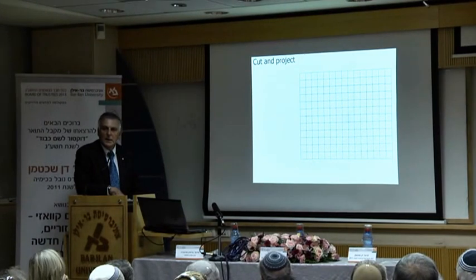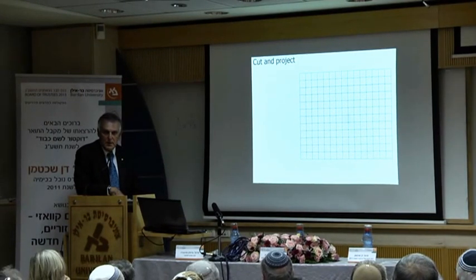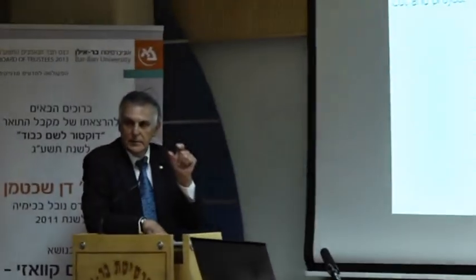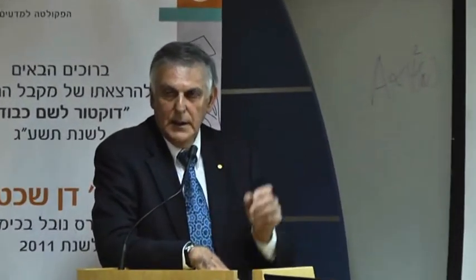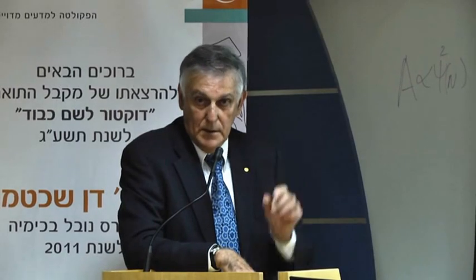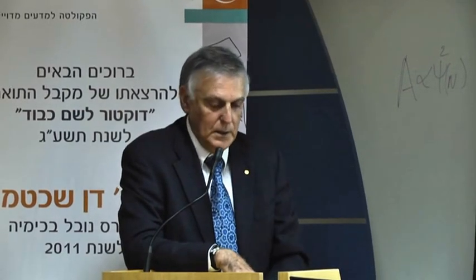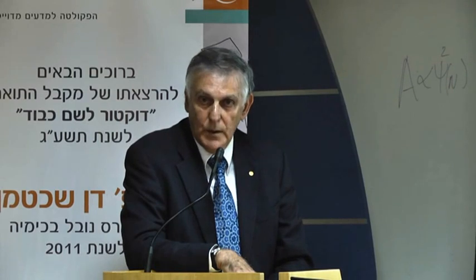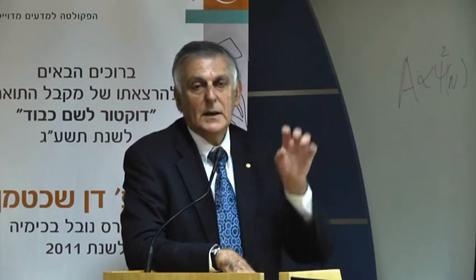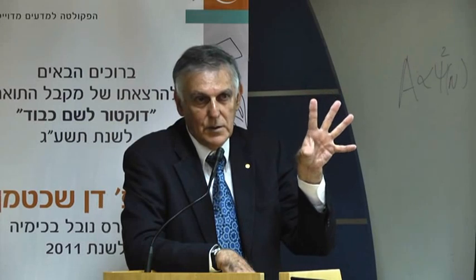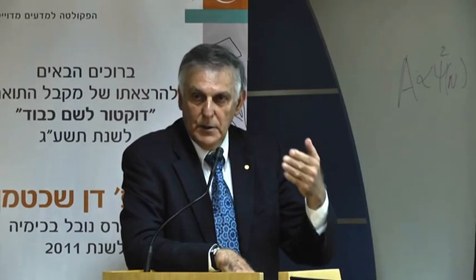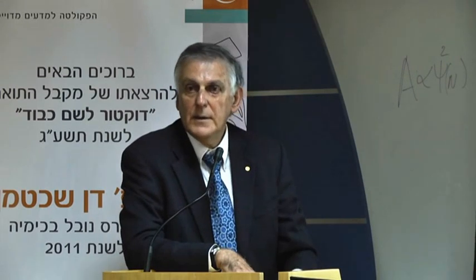We can take a periodic lattice in any dimension, make a cut and project, and from this operation of cut and projection, we'll get a quasi-periodic lattice in a lower dimension. We can take a periodic lattice in higher dimension, make a cut and project, and obtain a lower dimensional quasi-periodic array. And here is how I do it.